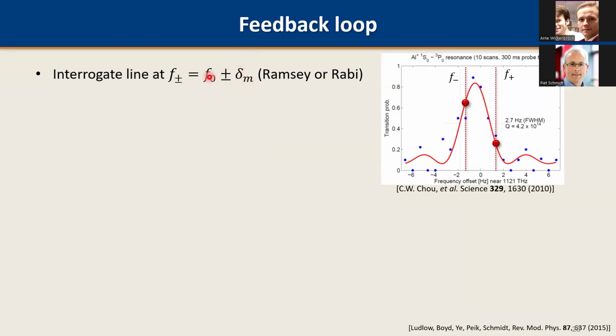We suppose we know the transition frequency, where that is, and how large the step is that we would need to make to get to the half excitation point here at roughly 0.5. So we apply that step, measure the probability of excitation, go to the other side, and measure the probability again. Then most likely we will end up in a situation like this, where there's an imbalance, because we did not in fact start at f0, but our laser has drifted in the meantime, and we start at a different frequency value, much more in this area. I've mentioned that delta M is chosen such that under ideal conditions we get half excitation here on the 0.5 scale.